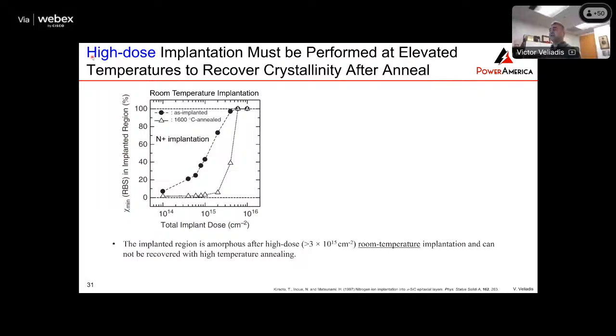And then let's talk about the high dose right now. If you look at the implant dose here, this basically gives you the disorder of the implantation. If you have high dose room temperature implantation and you do not anneal, you can see that once you exceed 10 to the 15th, there's a lot of disorder. So the wafer becomes garbage. And even when you do the anneal at 1600 degrees, once you exceed about 3 times 10 to the 15th, the disorder goes up, and then the wafer is not usable anymore.